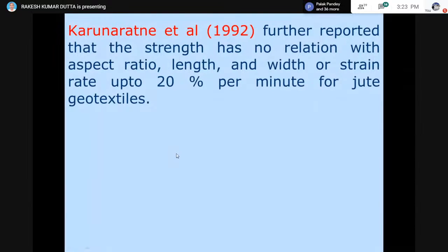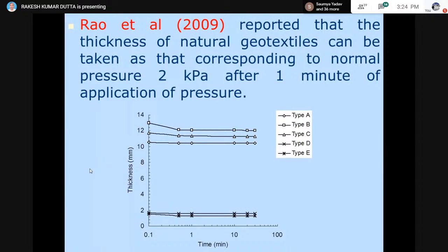Then Karunaratne in 1992 further reported that the strength has no relation with aspect ratio, length and width, or strain rate up to 20% per minute for the jute geotextile. This was another study reported by Karunaratne in the same paper. Keeping all these previous studies in mind, Professor G.V. Rao, K. Balan and myself were involved in a study where we picked up all the ASTM standards developed for testing polymeric geosynthetics, and all those test procedures and strain rates were applied to naturally available coir fibers and coir geotextiles.